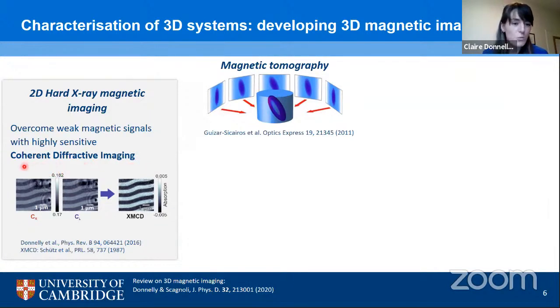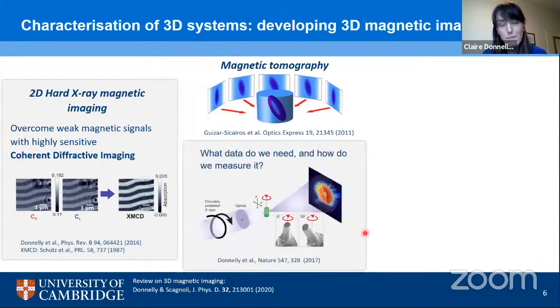So to give an example of how this works with XMCD, we probe our sample with circular right and circular left, and we can take the difference between these two images to isolate the magnetic contrast with high resolution. And here's an example of some iron gadolinium worm domains that we looked at. So we have our first piece of the puzzle. The next question is, what kind of combination of these 2D images do we need to measure in order to probe all three components of the magnetization? And it soon became apparent that a single rotation axis, which is commonly used for standard non-magnetic tomography, was not going to be sufficient. With that, you would only probe two components of the magnetization.